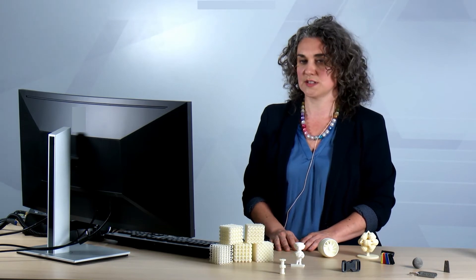The powder from the part cake can be refreshed. Industry uses up to 70 percent of the recycled material and mixes it with 30 percent virgin and reuses it that way. So you don't lose all that loose powder that wasn't used in a build.